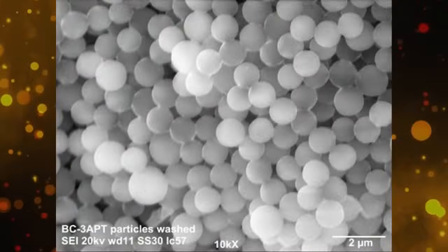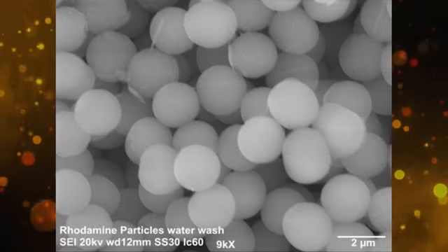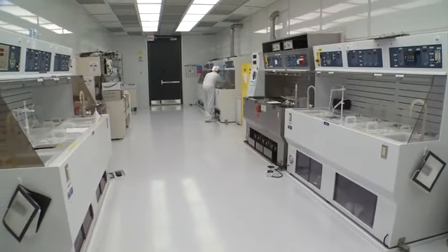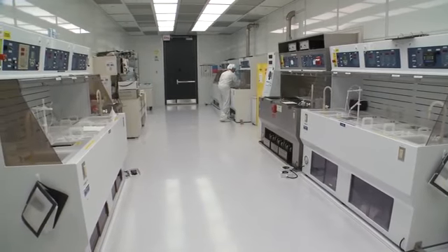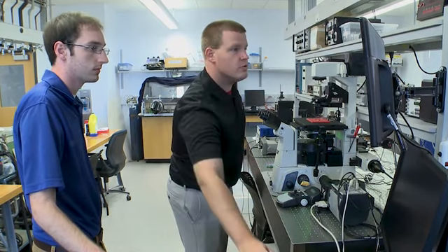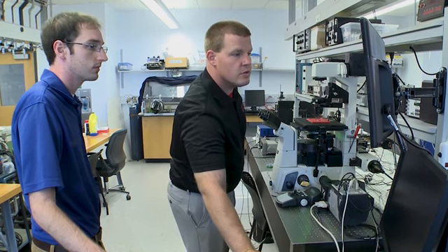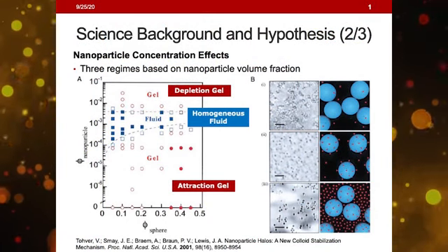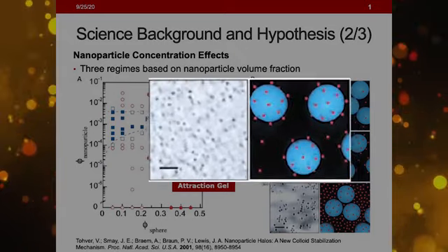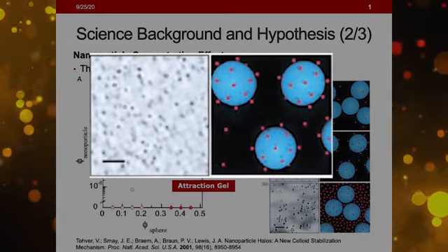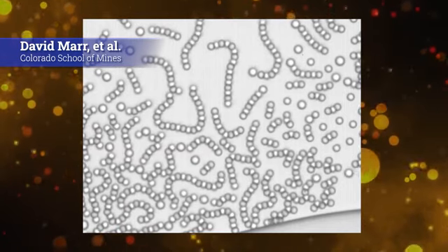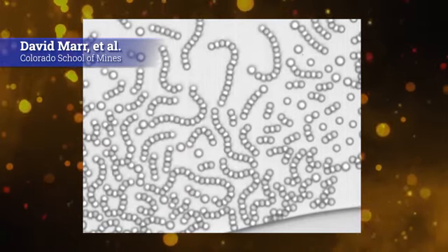With colloid manipulation, when you apply an external field, whether that field is gravitational effects, electric fields, temperature, magnetic fields, with all of these manipulation techniques, you can, in theory, manipulate not only the crystallinity of these colloids, but also the space in between them. And if you can dynamically manipulate these particles and their spacing, you can control, for example, optical properties, whether they manipulate light in a certain direction or they're selective to a certain wavelength of light. You can manipulate their mechanical properties and also their thermal properties. So now you have a dynamically tunable material that could be used for a variety of applications.